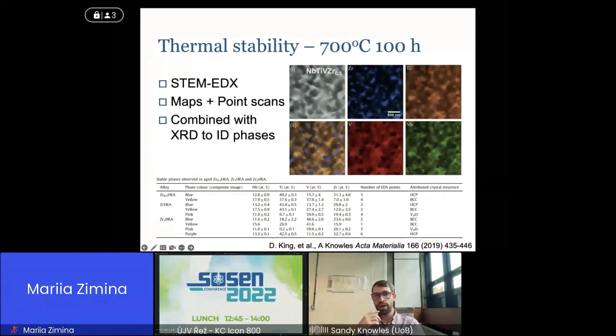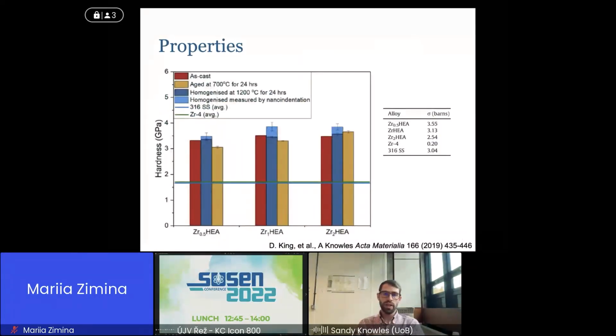So we went into more detail to work out exactly which phase is which, going into TEM, doing composition and linking that to the XRD and diffraction to identify the phases. Then we went on to compare the basic mechanical behavior. This was a very preliminary study where we're just looking at hardness. These things are about twice as hard or twice as strong as the zirconium and steel currently used. So you might be able to make an argument that if you can make things a bit stronger, you can also make them a bit thinner. So maybe there are some advantages to be had there.